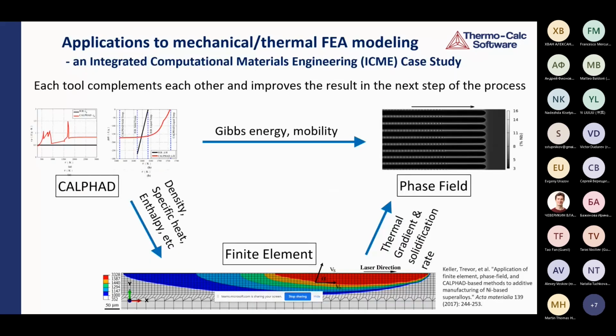Another example was actually shown in an article published in 2017. It was an application to mechanical thermal FEA modeling. So the learning is actually that each tool complements each other and improves the result in the next step of the process. So from CALPHAD we can get the density, for example, specific heat, enthalpy, and so on, to feed the finite element simulations. And then the finite element simulations could give thermal gradients and solidification rates for doing phase field simulations, for example. And CALPHAD could also support the phase field with Gibbs energy and mobility data.